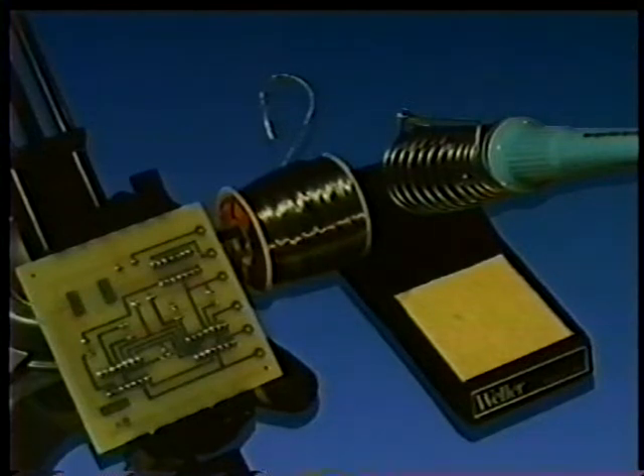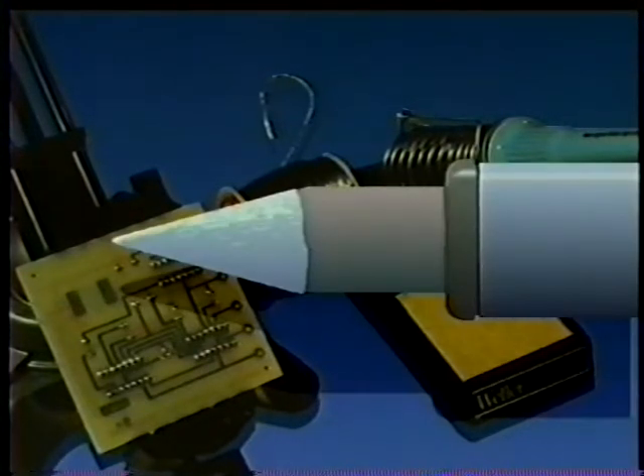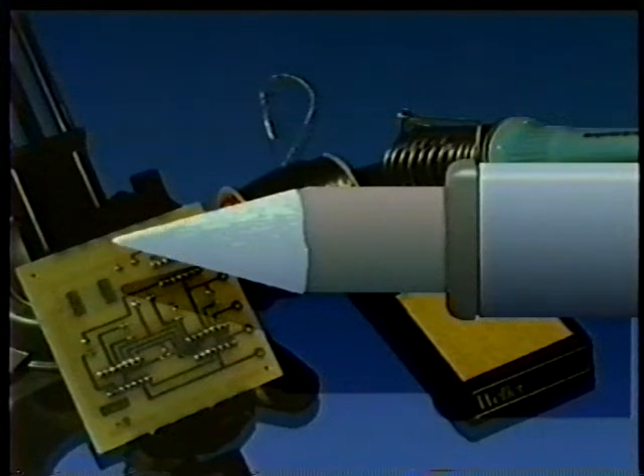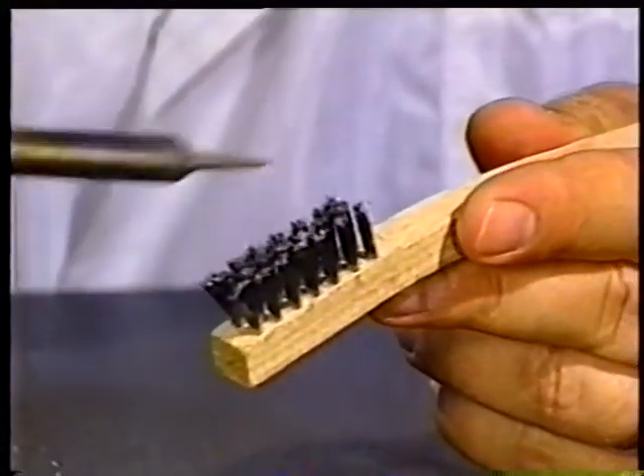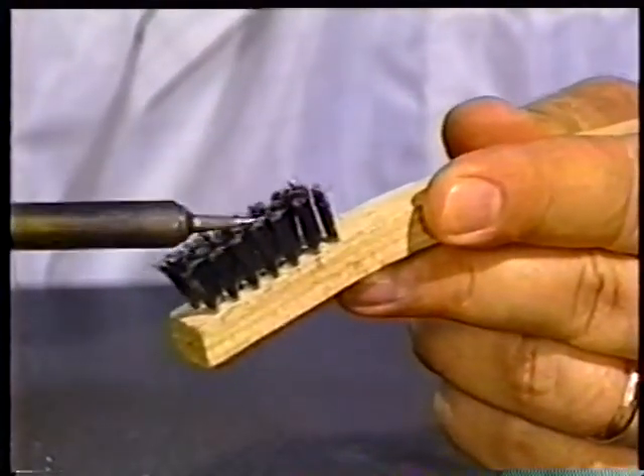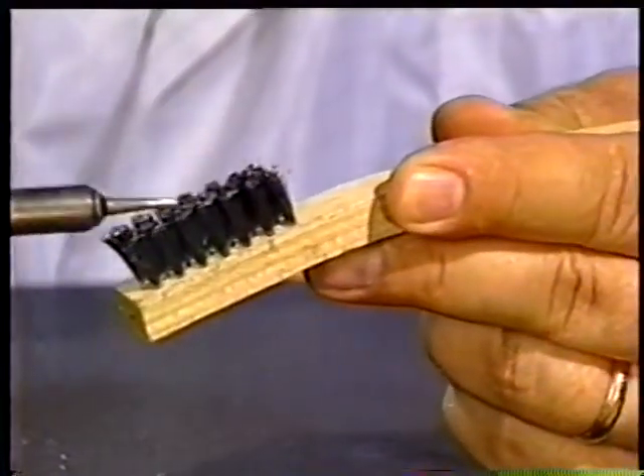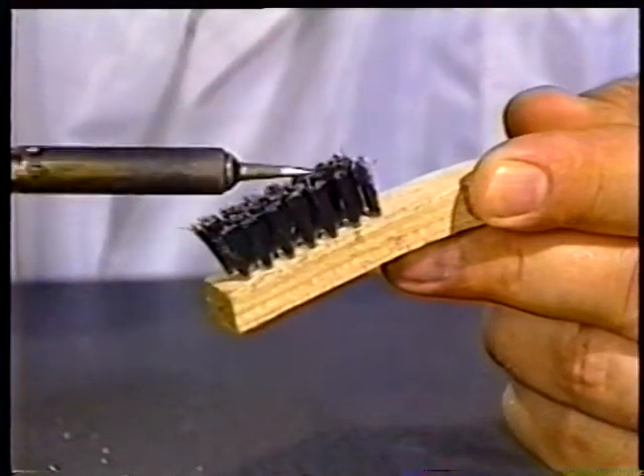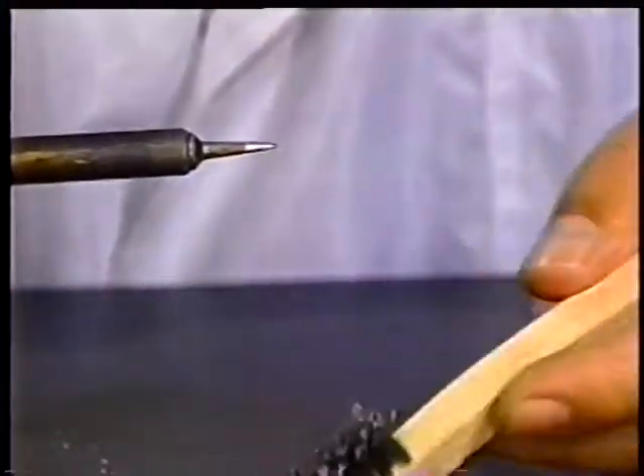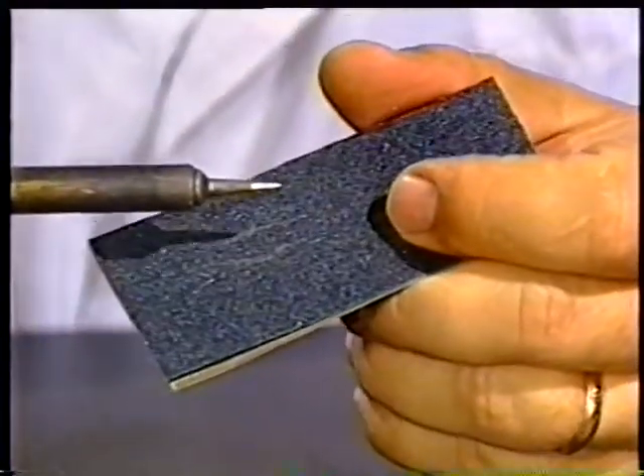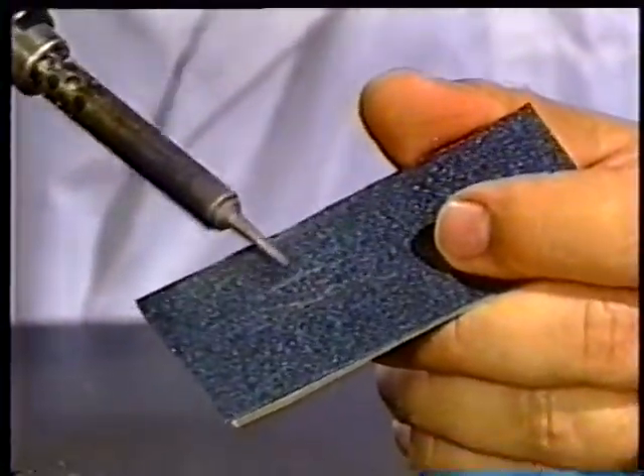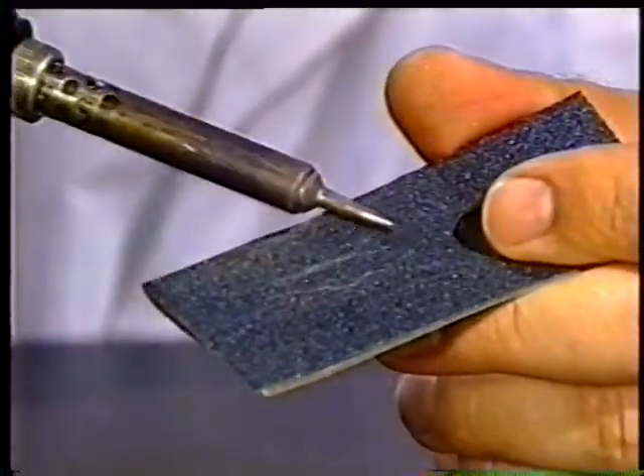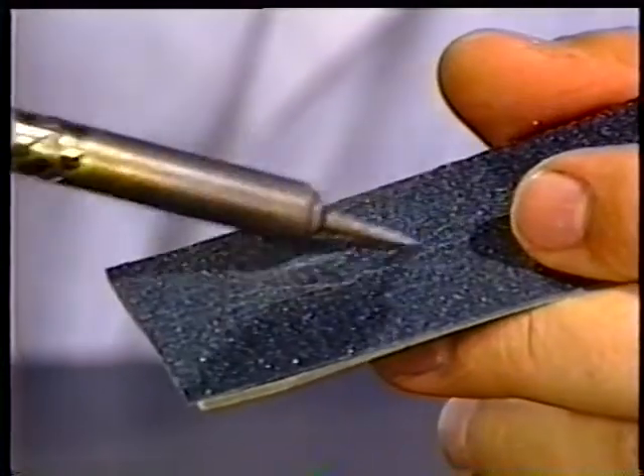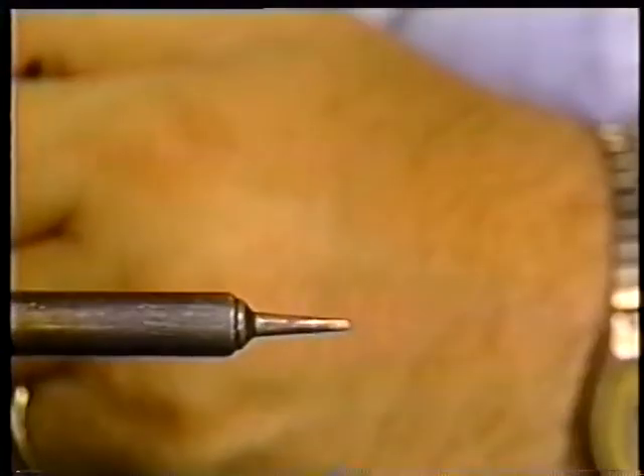Because of the reactions of air and flux upon the surface of hot metal, oxides form on the tip as it idles and cools. For reliable solder joints, these oxides must be removed. Therefore, the first step in good tip care begins before the soldering starts, while the iron is cold. While the iron is at room temperature, a wire brush can be used to gently remove the scaly oxides from the tinned area of the tip. An abrasive polyurethane foam stick or a 100 grit emery cloth can also be used to effectively remove the oxide. Care must be taken not to damage the protective plating of the tip.